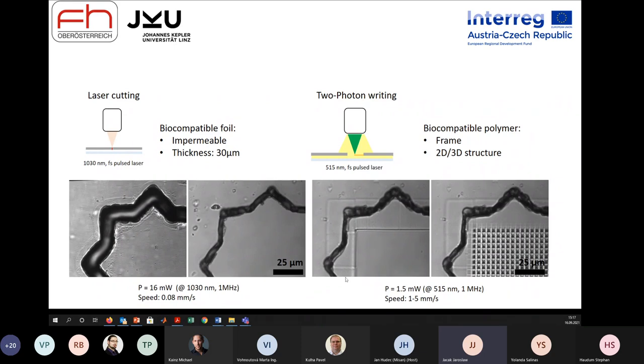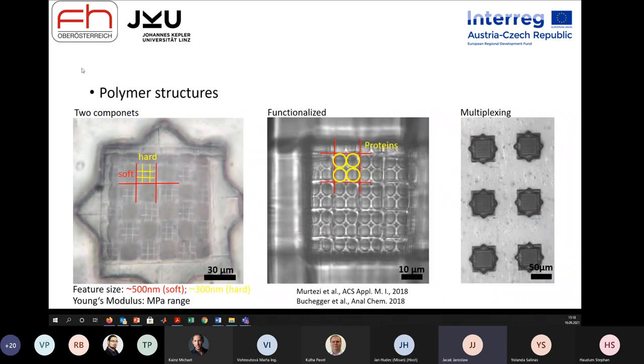Then we were writing with two-photon a polymeric carrier structure on the border, in order to make sure that we get rid of the not nicely cut plastic leftovers, and then we printed a 3D structure into this hole. The whole membrane thickness was 30 micrometers. The material of the membrane was PET, so it was easy to cut, and due to two-photon structuring, we were able to structure in the ranges of micrometers down to 100 nanometers. So this is what we have done basically.